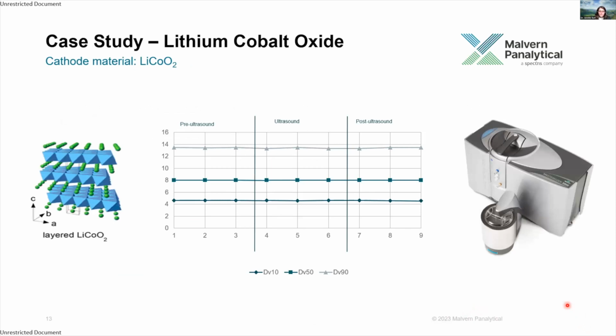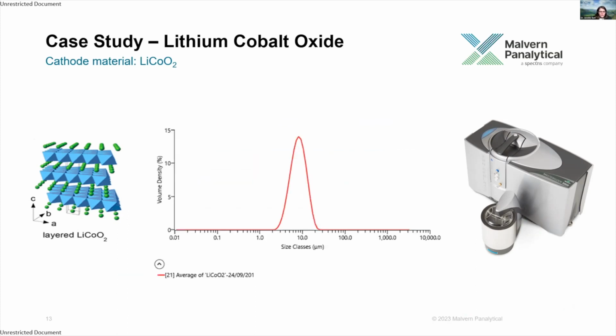So now I'm going to look at some examples of battery materials that have been measured on the Mastersizer 3000. And we're going to look at both the particle size distributions as well as the dispersion trends, which we use to investigate the state of dispersion of the material as we measure it on the Mastersizer. So first, here we have a lithium cobalt oxide powder that's been dispersed in water with the addition of a surfactant to help wet the powder. From the trend graph, you can see that the particle size distribution is stable both before, during, and after the application of ultrasound, suggesting that the sample is well dispersed without the need to input extra energy. If we then look at the particle size distribution, we can see that it's monomodal, and the particle sizes are relatively large for a cathode material, so this should be giving us higher specific energies.